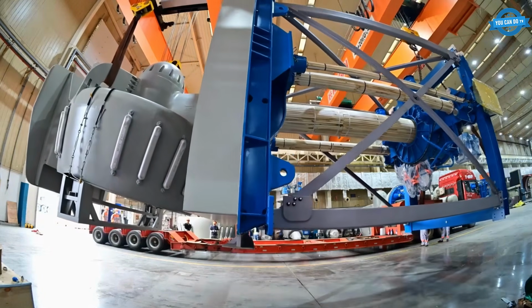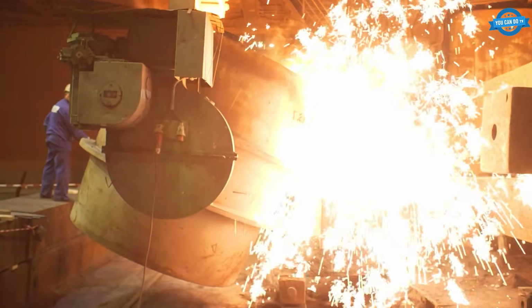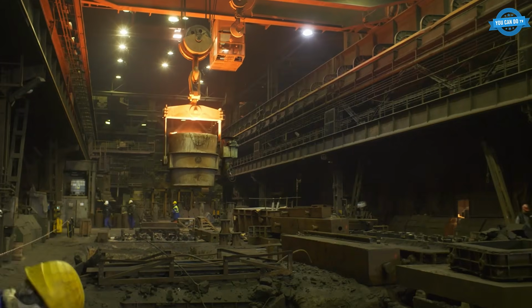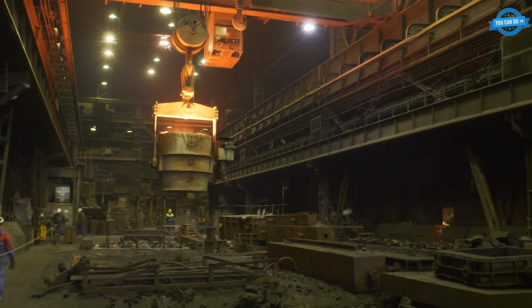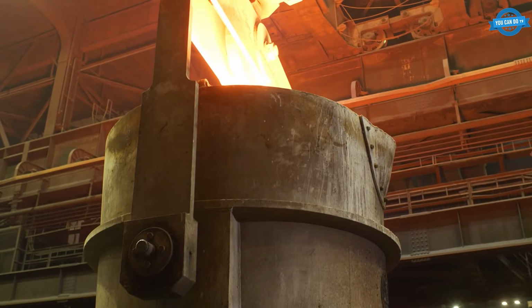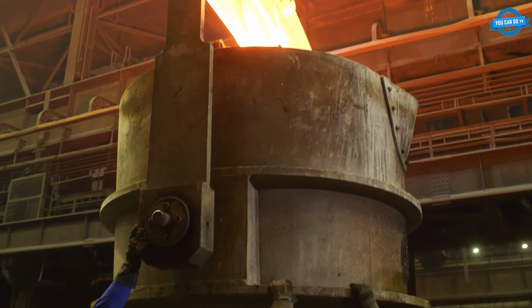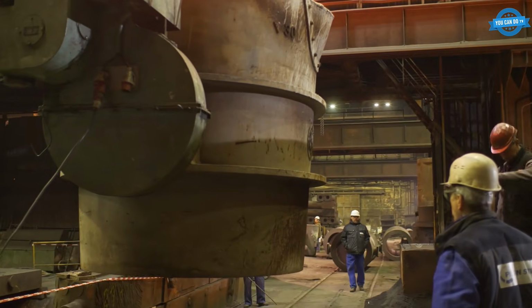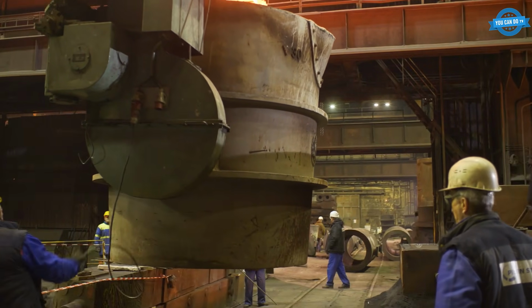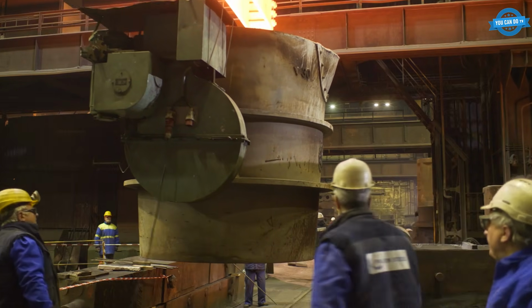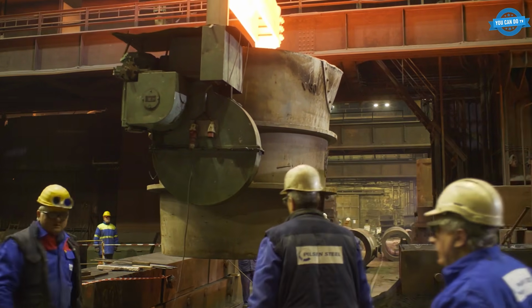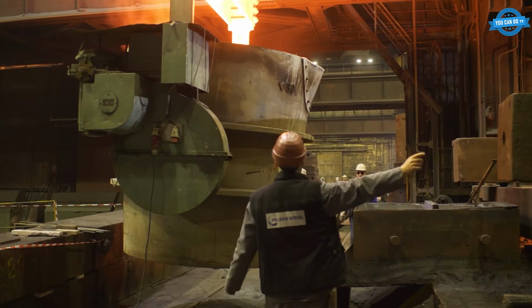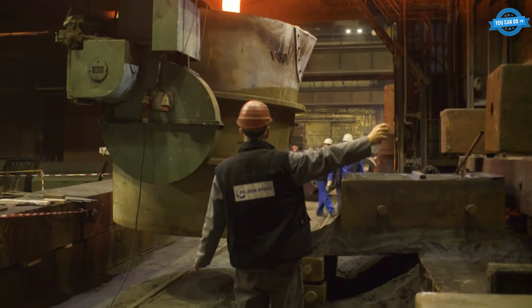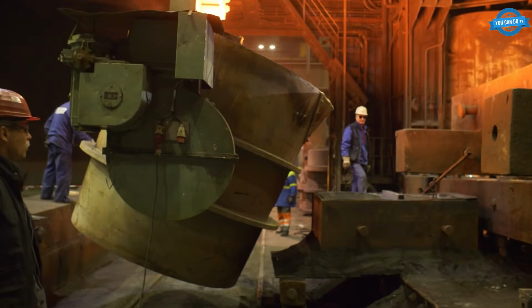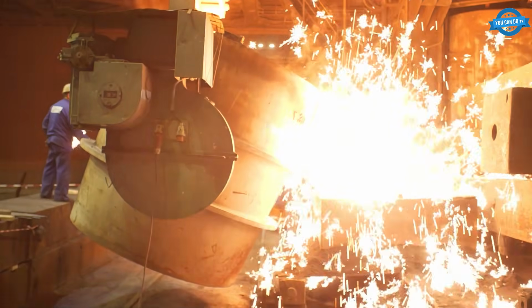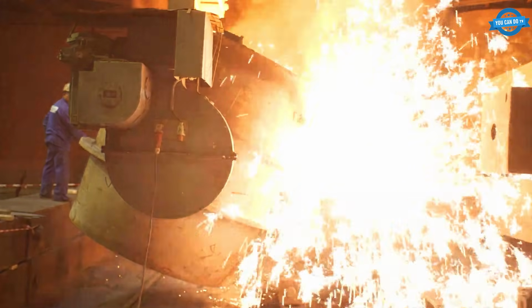part is finished. Before engineers can shape anything, they have to control the metal while it is still liquid, while there is still a chance to keep the flaws out. Heavy overhead cranes move a giant pouring ladle filled with glowing liquid metal into position above the molds. Engineers check the nozzle at the base of the ladle first, priming it with a small test flow to warm the system before the real pour begins.